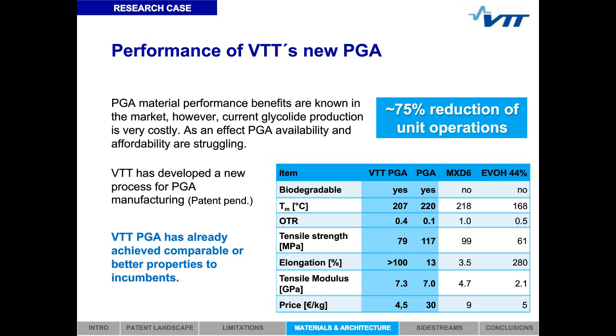The major limitation of industrial, commercial PGA is that the production costs are very high. This patented VTT process can significantly reduce the production costs of PGA and simultaneously maintain the excellent oxygen barrier properties and mechanical strength properties that PGA has. So overall, this VTT PGA is very much comparable or even better than the existing materials that are nowadays used in applications where high oxygen barrier properties are needed.